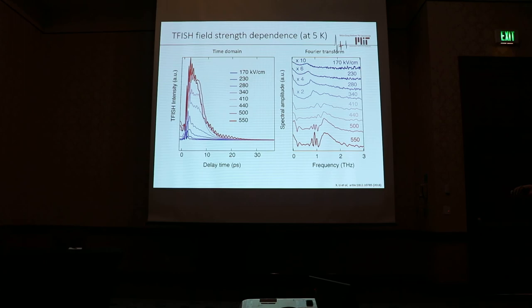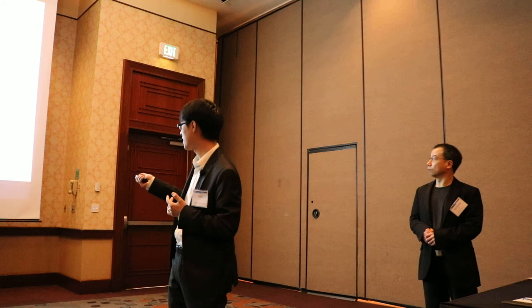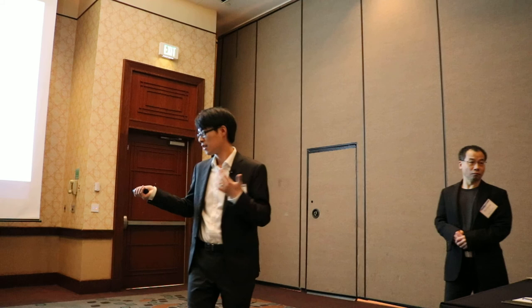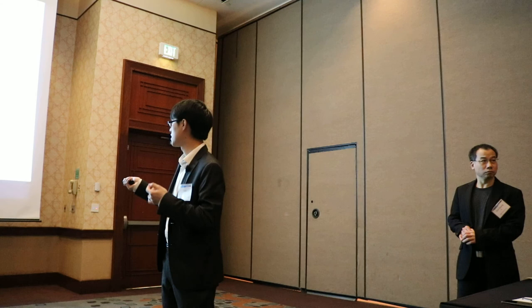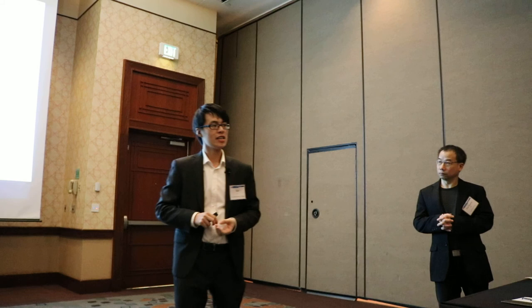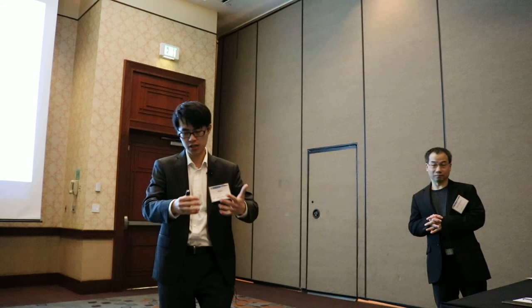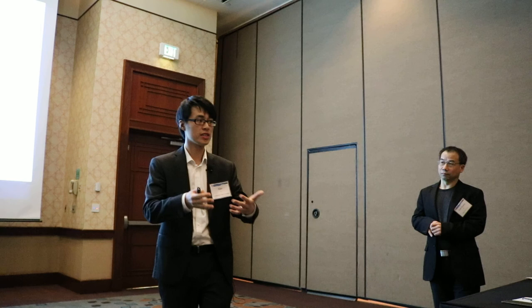We have evidence to show that this very broad peak is the Raman-active mode — although this is the IR-active phonon spectrum, we are still able to see a Raman-active mode, because we believe it is the A1g mode associated with the oxygen cage rotation. The mechanism here is basically that when we drive the IR-active soft modes hard enough, we can have the so-called ionic Raman scattering, which is essentially anharmonic coupling to the other modes. This gives rise to the excitation of these Raman modes.